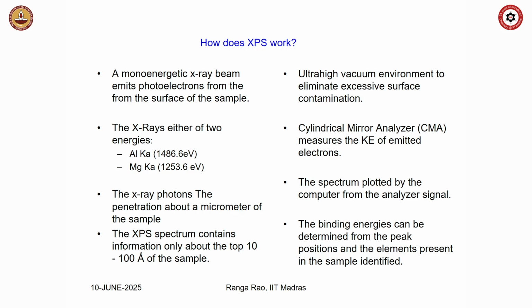Okay. How does XPS work? For XPS to work, you have to have a monochromatic X-ray beam. The X-ray beam that you are using should have a very precise energy. X-rays of either of two energies, as I mentioned already, penetrate up to about a micrometer, but the photoelectrons coming out from 10 to 100 angstroms are the ones which will give you the correct information about the elements present in the sample. In addition to all these, you need vacuum. Why do we need vacuum?